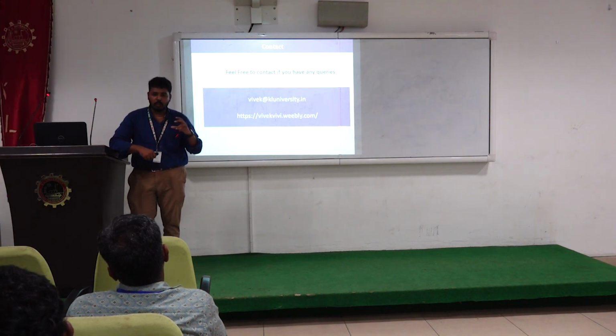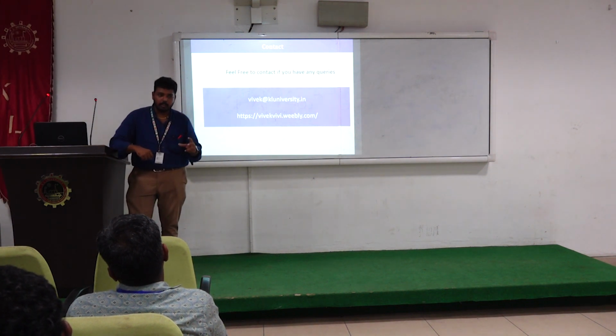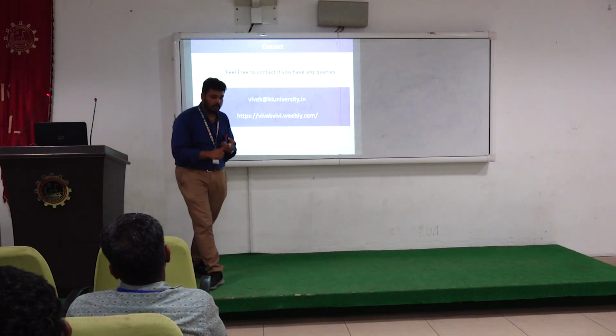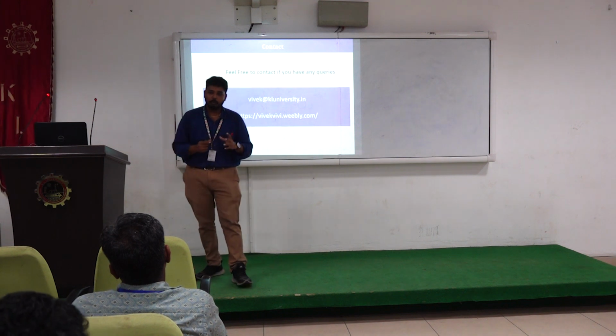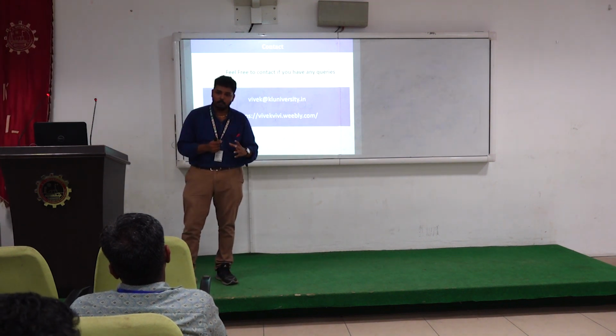So one approach I am thinking of is a high dielectric constant in the case of a triboelectric material, and a high piezoelectric coefficient for the piezoelectric material. There are commercial materials like PMN-PT and lead zirconate titanate. These materials have a very good piezoelectric constant. Those materials can produce very good electric output.